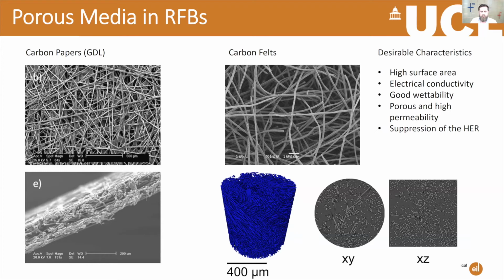which is a bit of a problem in vanadium flow batteries. If you go to too negative voltages on the negative electrode, then you're going to start to split some of the water into hydrogen, and that leads to capacity fade and other problems in the flow battery as well. So this is why they're quite often just carbon felts, and they're not decorated with highly active metals like platinum, for example, because that would just catalyze the HER.